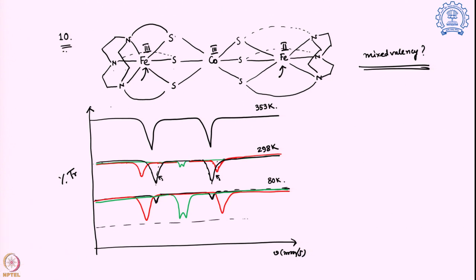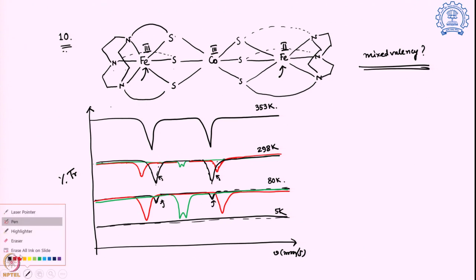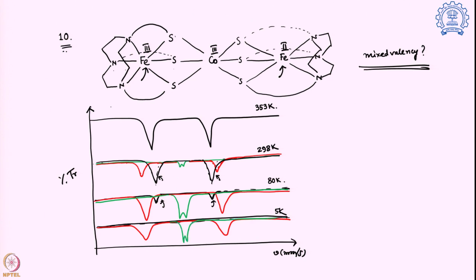We go to 5 Kelvin and we see nothing of this old peak over here. They are almost gone. What happens to this red and green? So the red one actually remains over there. The red one remains over here, while the green one also starts dominating. So no trace of the original black trace, no signal from there.